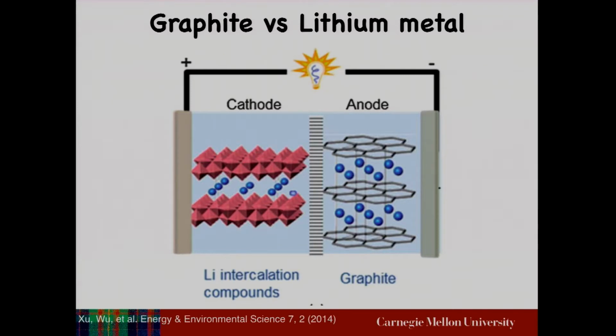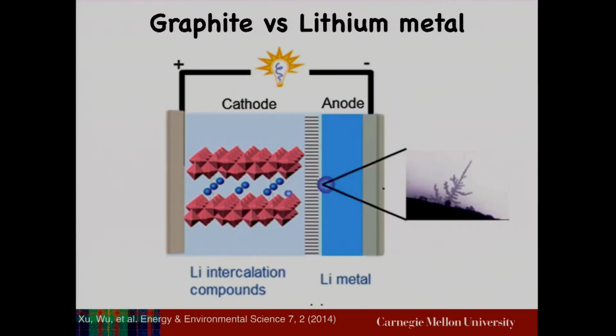Now, what you would like to do is to try and remove as much of the extra material as possible. The extra material in the anode is the graphite sheets, the graphene sheets. And so the holy grail is essentially to do away with graphite itself and just have pure lithium metal. Now, the challenge here is when you try and cycle lithium metal back and forth, which means you move it from the anode to the cathode, back to the anode, and so on, when you charge and discharge every single day, there are these mossy dendritic type structures, very similar to the structures that you've seen in snowflakes. Actually, it's the same underlying physics that goes on between these two cases. And so these dendritic structures often grow through from the anode to the cathode, and it creates a short circuit. And typically, when you have liquid electrolytes, that leads to fire and other unwanted things.